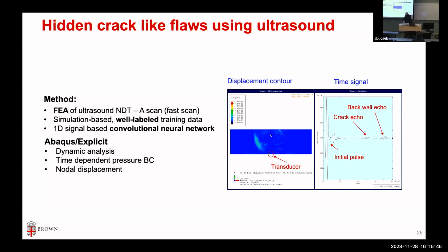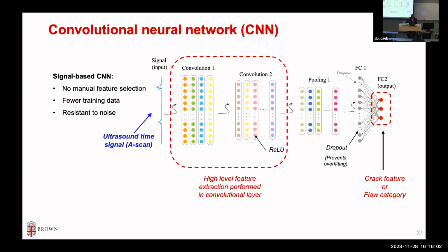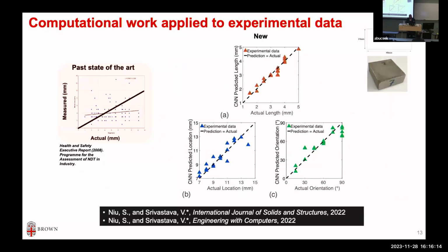And what you get as the signal is you send some sine wave, and all you're getting is basically reflection back, a very small signal. And this perturbation in this signal is coming back because something is there, and the changes in this will tell the size, the location, and stuff like that. And again, we had a neural network architecture. Computation is still non-trivial, but nonetheless is orders of magnitude better than doing the experiments, which are quite expensive and impossible to do.